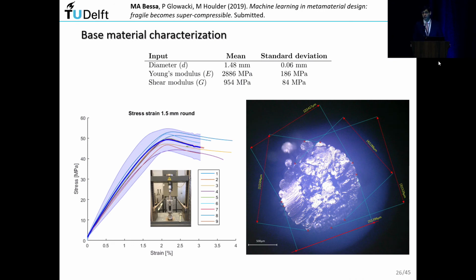Okay, so what do we need to do? All right, so first, you characterize the base material. In this case, it's PLA. So very simple tests, okay? Uniaxial tension, compression, shear, and that was about it. And you define the diameter. So the specimen was a longeron of 1.5 millimeters. You define the mean values and the standard deviation for all of this: Young's modulus, shear modulus, diameter.